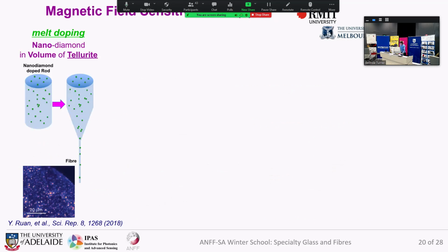And so we started to do this. We used tellurite glass, a low melting glass, thinking it would help the particles survive when we put them into the hot glass melt. We started with melt doping, having the particles everywhere.